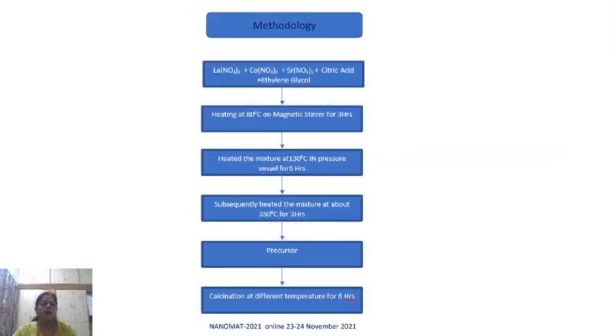Methodology. A stoichiometric ratio of lanthanum nitrate, cobalt nitrate, strontium nitrate, and citric acid were dissolved in ethylene glycol. The mixture was stirred on a magnetic stirrer at 80 degrees Celsius for 3 hours. The solution was then heated in a pressure vessel at 130 degrees Celsius for 6 hours. The solution was now transformed into a gel.